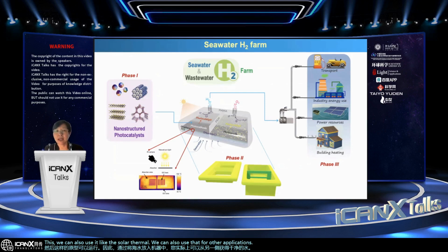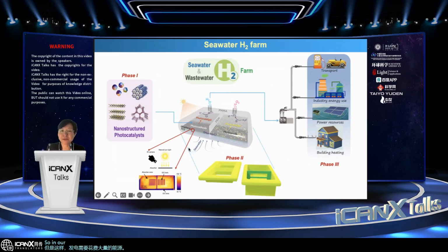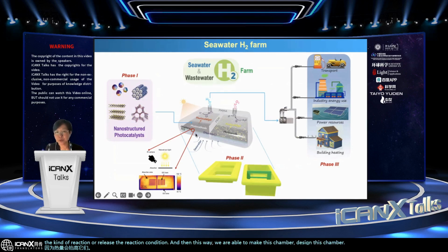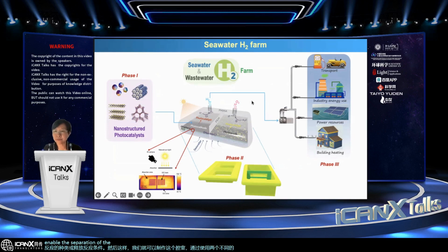For example, hydrogen generation. Most hydrogen generation is currently based on electrolysis, which means using electricity to split water. But this way, it costs a lot of energy to generate that electricity. So in our case, we have this photothermal generation. Basically, we have our graphene oxide layer, graphene layer, and we load it with photocatalyst. This photocatalyst can help to split water by making use of the heat, because the heat elevates the reaction or relaxes the reaction condition. This way, we are able to design this chamber using two different catalysts to enable the separation of the water. Such a device can be made modular and then used to produce hydrogen for different applications.